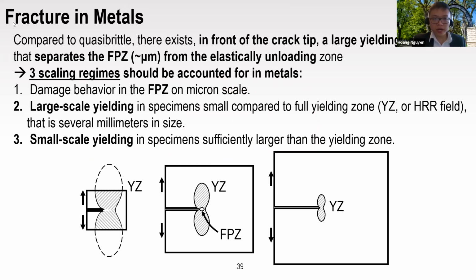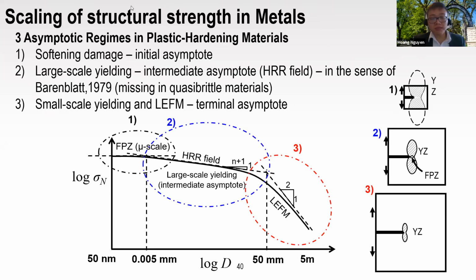In this case, the story is a bit different. In metal, instead of a very large fracture zone, we have the yielding zone here. And the yielding zone, as I mentioned at the beginning, is the zone or the volume where the material becomes hardening. In large scale yielding, such a zone can cover a very large part of the specimen or structure. However, when the structure becomes bigger and bigger, that ratio becomes smaller, and the yielding zone is completely contained within the specimen. And this difference calls for another theory to scale the structural strength to extract the GF.